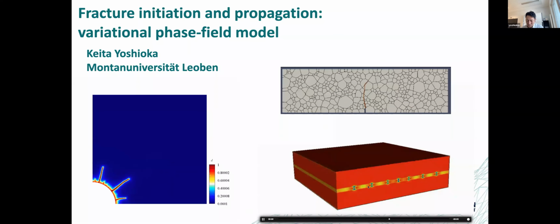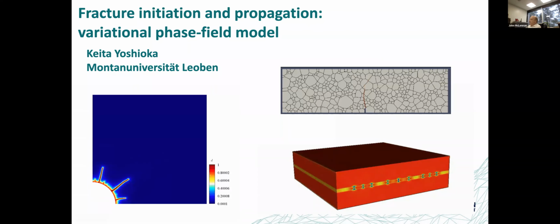at some point, this uniform damage becomes unstable. Meaning that if we compare two states of energy, one has a localized damage and the other has the homogeneous uniform damage, the localized damage has a lower energy state, so it is more stable than the uniform damage state. That's when the damage starts to localize. Initially damage is uniform, as you can see, but then at some point it starts to localize because uniform damage is no longer stable. Okay. Hopefully that answers the question. I think it did. Yeah.